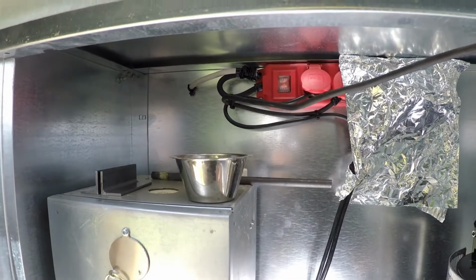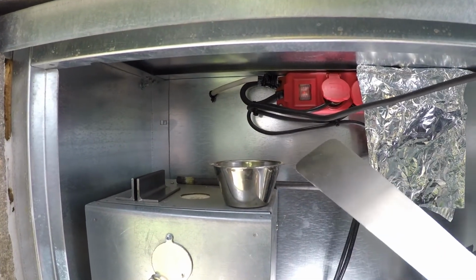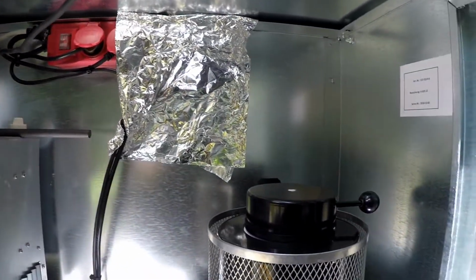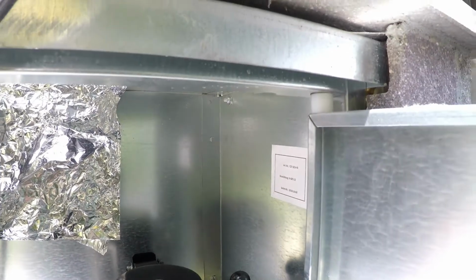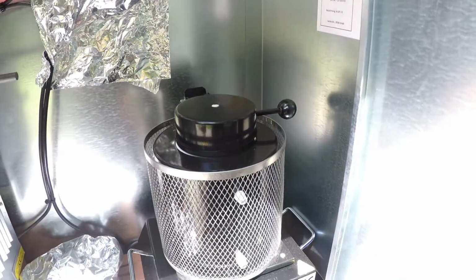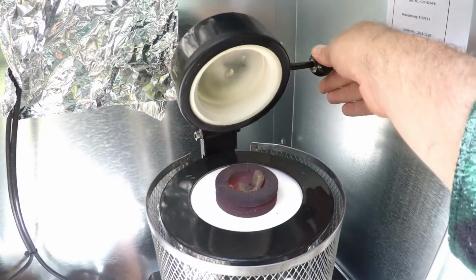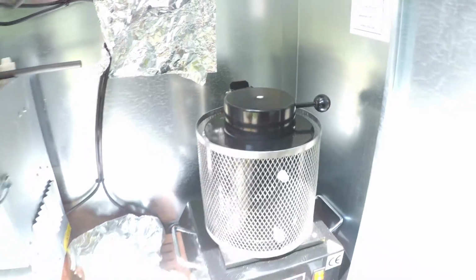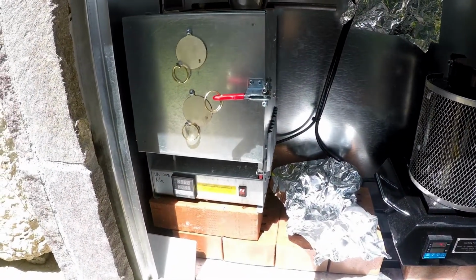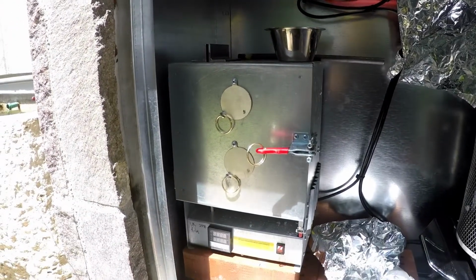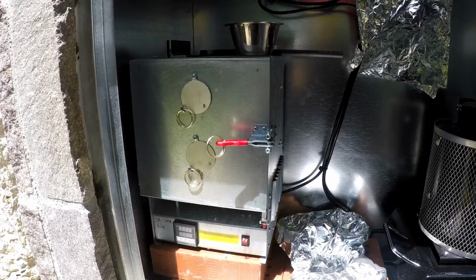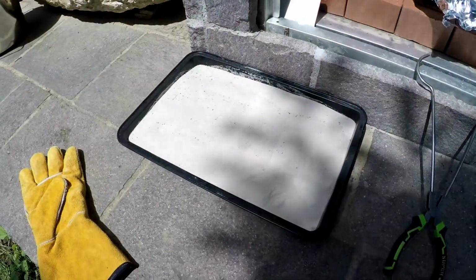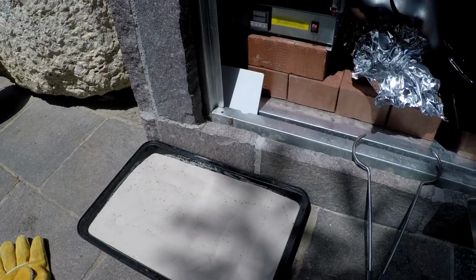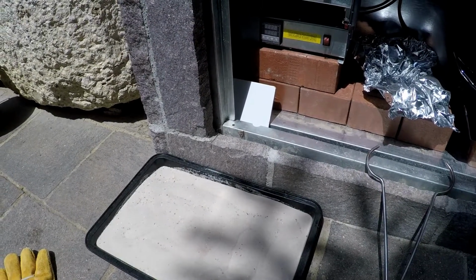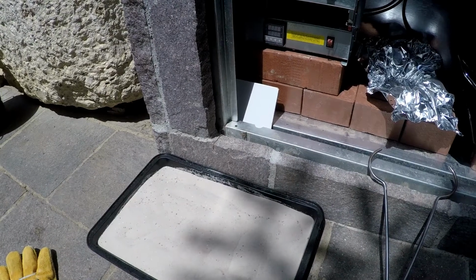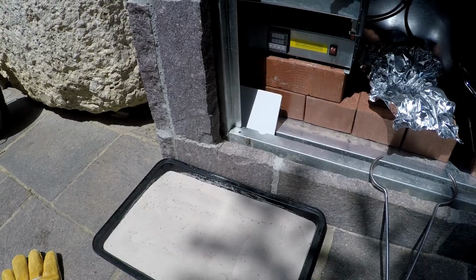Okay, next step before casting. On top we have here the bronze spare parts preheated, and I add already the bronze to the furnace. It is already melting. The mold is in the kiln. It is heated up to 700 degrees, and I will soon take it out and place it here in the sand for the casting process. It cools down there for about 10 minutes to maybe 600 degrees, and that's the perfect temperature for the mold to fill it then with the 1100 degrees hot bronze.